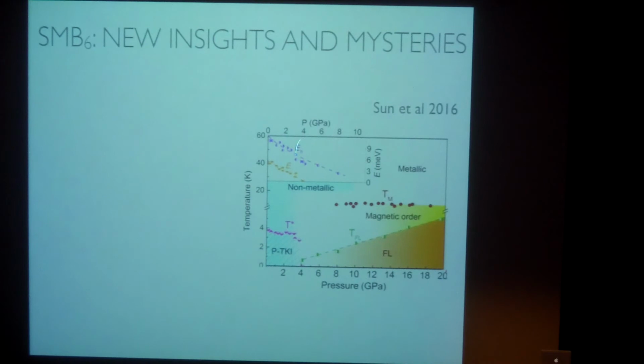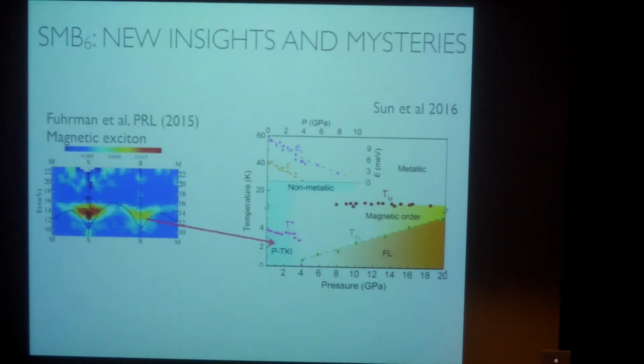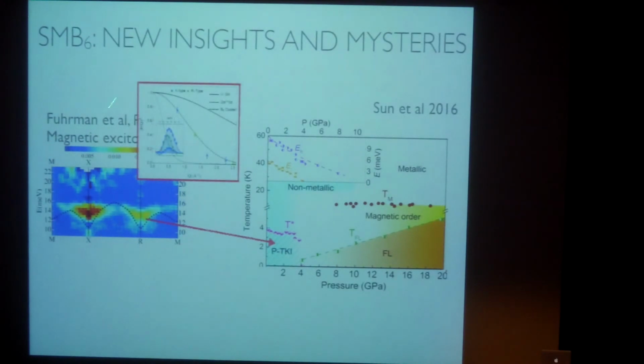Here's the phase diagram as a function of pressure. This system goes from a topological insulator into some kind of metallic state and then develops magnetic order at higher pressures. If you do neutron measurements, you see magnetic excitons. And the form factor of those excitons is particularly peculiar. It's a d-electron form factor, despite the fact these are formed from hybridization with f electrons. And we don't understand that.